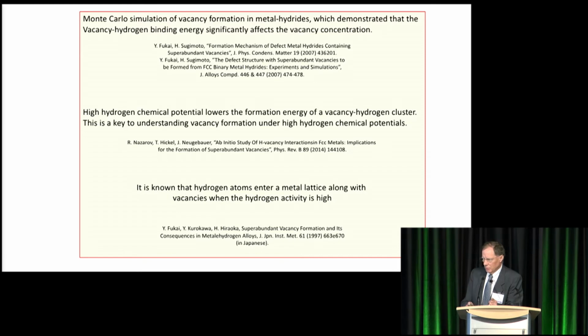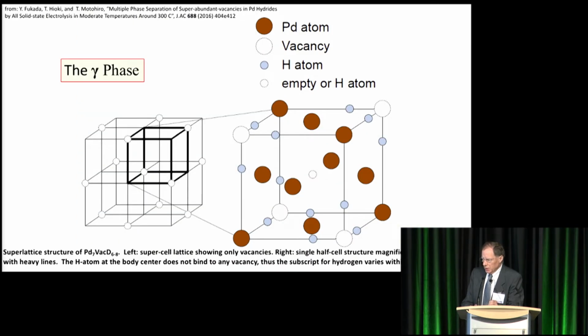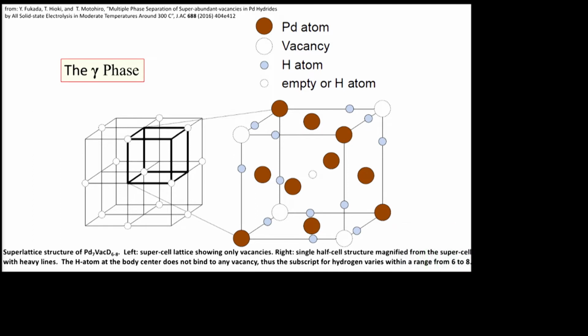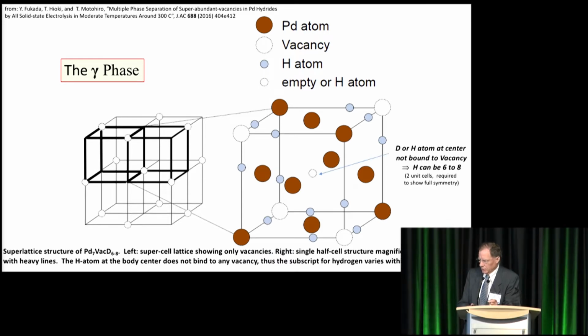I'm going to skip this. This is more papers confirming this, the basis of the fact that the structure is the most stable, lowest free energy form of the structure. This is the PD7 vacancy D6 or D7 or D8 stoichiometry structure, and the unit cell on the right is inadequate to fully contain the symmetry. You need 2 cells because instead of having all the corner atoms vacant, only half of them are vacant. So you need 2 of these to complement to make a unit cell.